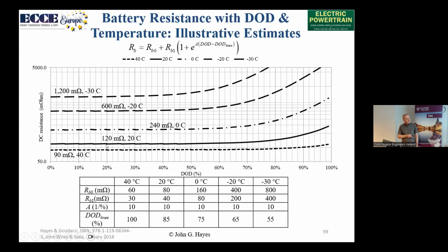So at 20 degrees C, the resistance on my pack looks like it's about 120 milliohms, 0.12 of an ohm. So all the current has to go through that 0.12 of an ohm. At minus 30 degrees C, that goes up roughly a factor of 10. And now I have a big problem. I've got a huge resistance there.